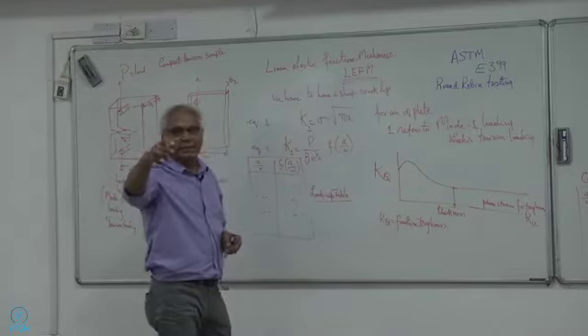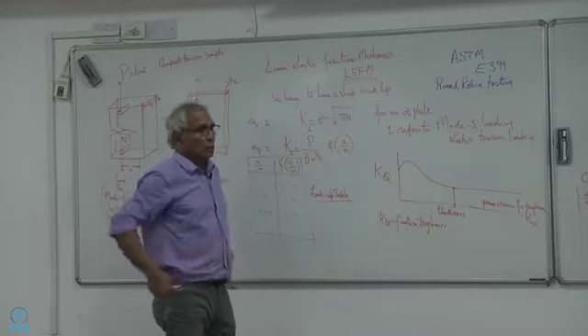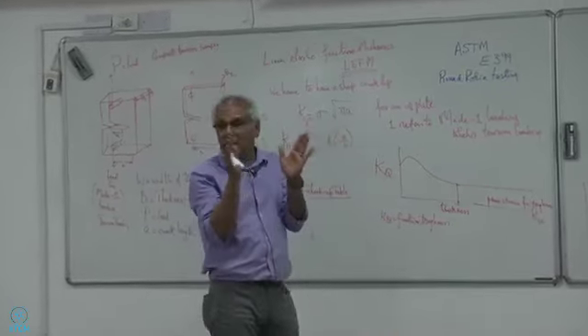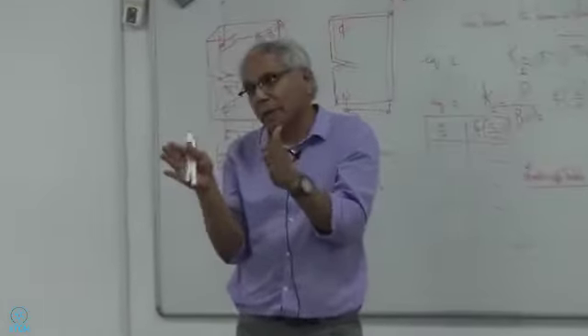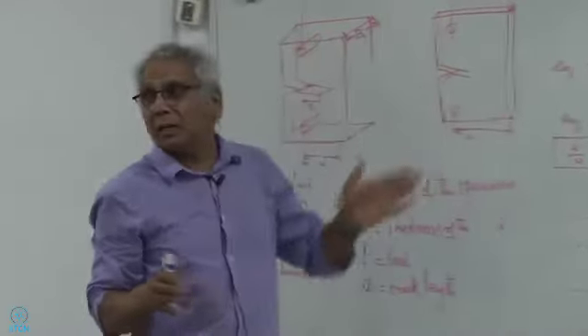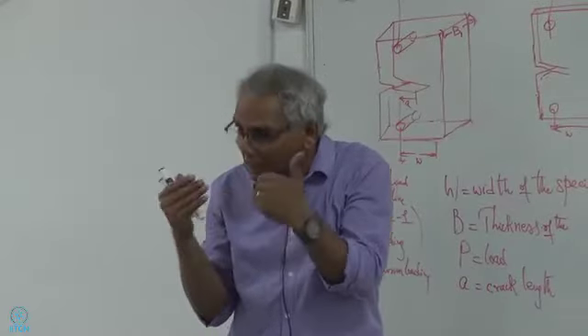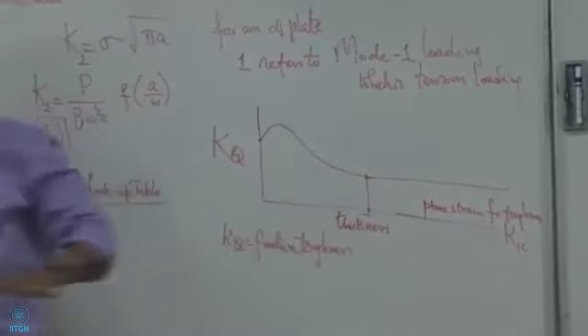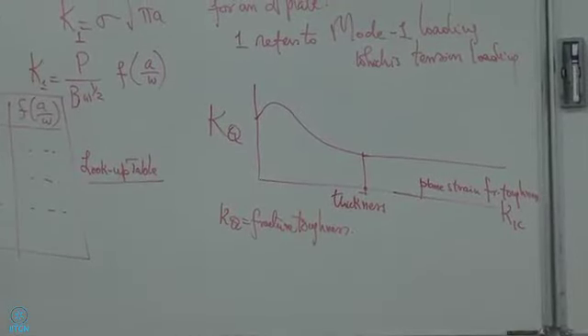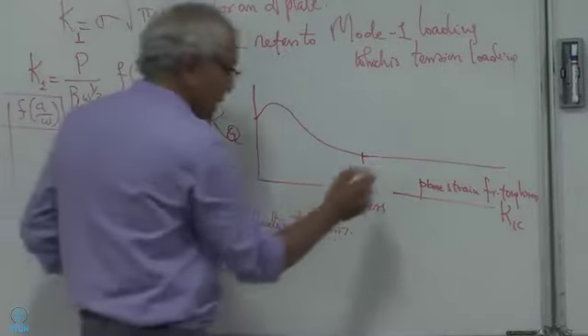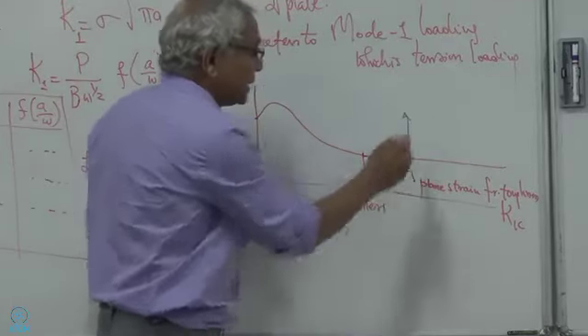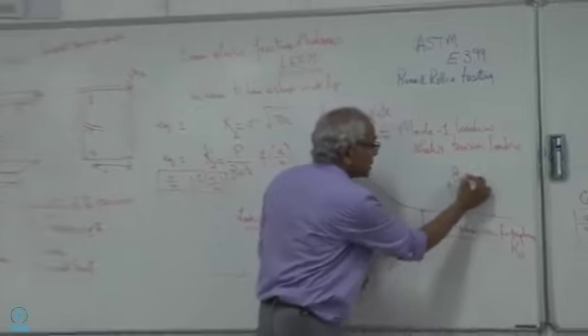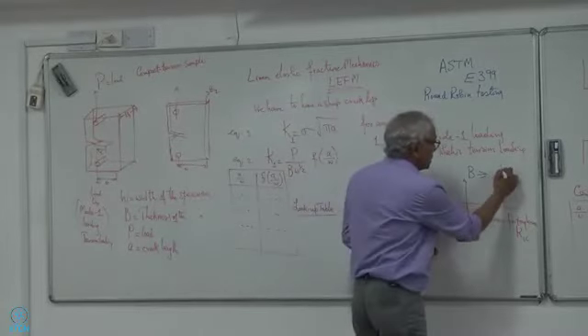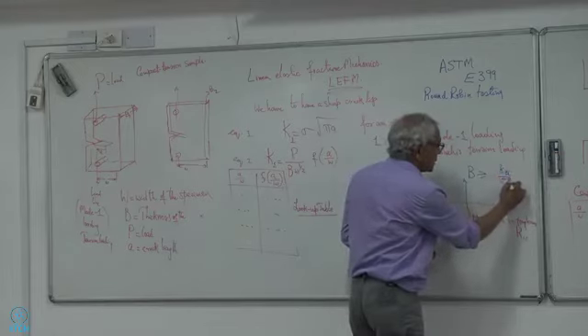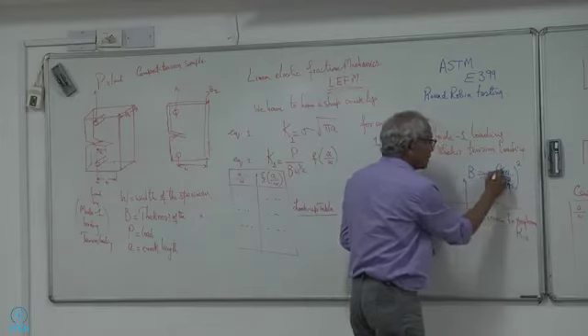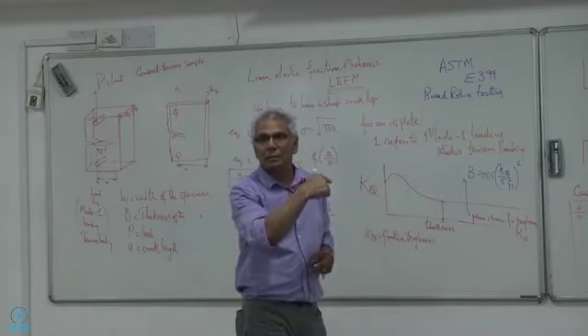So to answer his question, he was just asking a question along these lines. If I have a sufficiently thick material available, out of which I can machine a sufficiently thick specimen, I may be able to get this plane strain fracture toughness because it is thick enough. But what does it mean in terms of numbers? To meet this criteria of K1C, my thickness has to be greater than or equal to, I got to check this equation again, 2.5 times (K sub Q over sigma ys) squared. I think it's 2.5 here. Right? Okay.